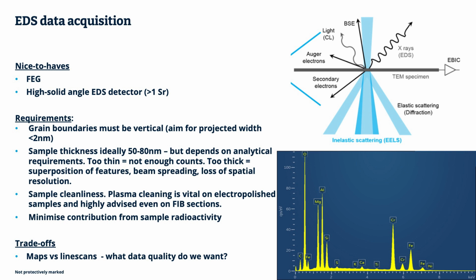Here's an example of an X-ray spectrum, and obviously, it's a statistical process, the thing is turning that into some meaningful compositional data. So things which will help us there are having a lot of counts in the spectrum, and in that case having a field emission gun TEM is enormously advantageous. Aberration correction adds another factor of 3 to 5 to the beam current that you can get into a small spot, so that is also a huge advantage.